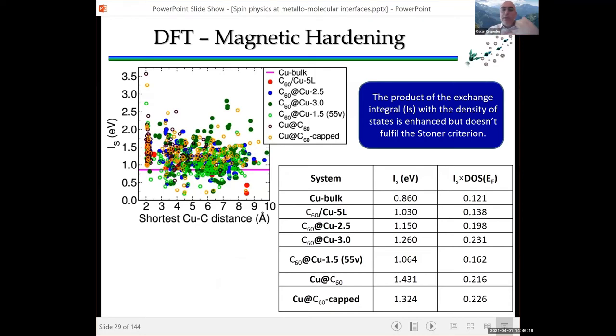This wouldn't be enough by itself to apply the Stoner criterion. You still don't beat the Stoner criterion, but what you do is you change the shape of the electronic structure at the Fermi level as well. So what you can have is an induced magnetization when you grow these samples in the magnetic field. That is what we do.